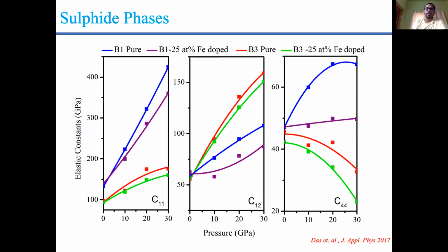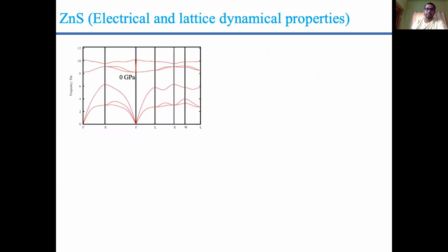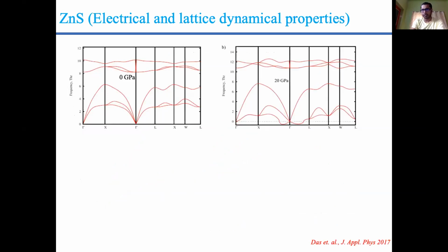Using lattice dynamics, I have plotted the phonon dispersion of the B3 phase at ambient condition as well as at high pressure, which is a little higher than the transition pressure. I started this calculation with a primitive cell of zinc sulfide, which contains 2 atoms. So for the phonon modes, we should get 6 phonon modes. Among them, 3 are acoustic and 3 are optical. The lower frequency modes are the acoustic modes.